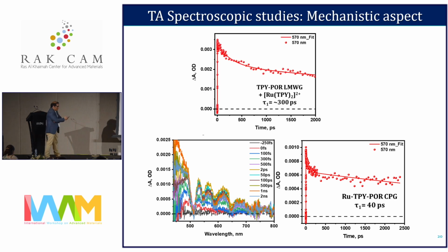When you have the physical mixture of this ruthenium terpyridine and the low molecular weight regulator, your T1 is 300 picoseconds. This indicates it is not as facile a process compared to when you have covalently connected the ruthenium terpyridine through the alkyl amide chain.